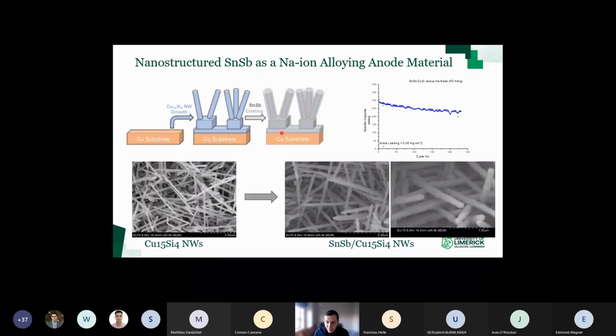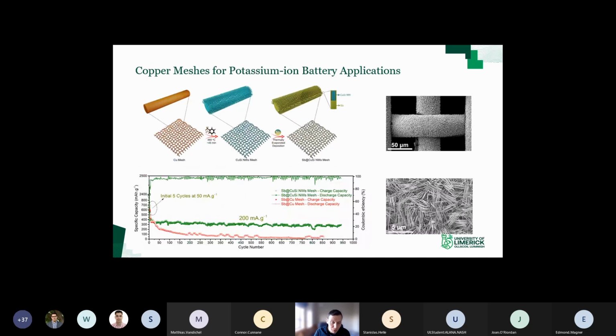Because we're looking at relatively novel materials here, Stephen has developed his own electrolyte concentration. He uses FEC additive with DME, and that gives the benefit of both the carbonate-based chemistry and the ether-based chemistry as well. He's gotten reasonably good performance with these. He's not long into this project, but he's gotten up to 250 cycles with relatively stable capacity retention. And actually, he has over 1,000 cycles with a bilayer on a planar electrode as well. So that's very promising.